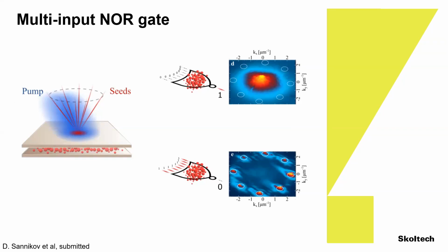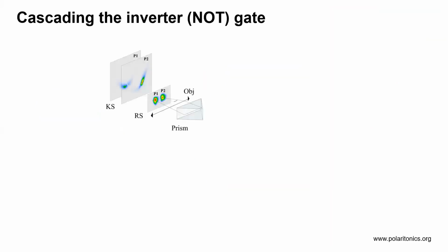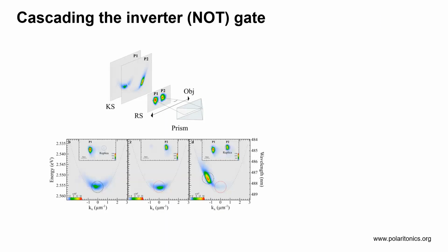Of course, if you have gates, as we have shown with the AND and OR gate, you need to be able to cascade them. Cascadability is very important for any logic operation. So we set out to cascade those. So practically, couple two of these NOT gates so that when the first one is off, you can operate the next gate. And I show you here in reciprocal space. When we pump one gate, I get the condensation. When I pump the second gate, I get condensation. And now, when I pump both of them and I take the light from one of these gates to the other gate, practically I can use the emission of the first gate to switch off the second gate.